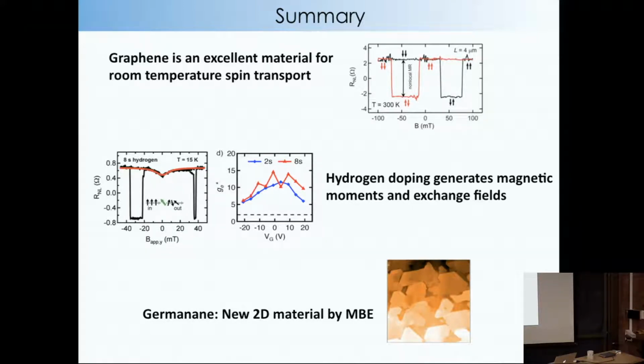It's actually a really great system because the sp3 bonding is the thermodynamically preferred state for germanium and silicon, but not for carbon. Actually, carbon wants to be more like graphite. But yes, you can do carbon; if you put enough hydrogen on it you've got a monolayer. People started by doing all this type of work with hydrogen on graphene, but the changes that you get are really drastic. It's like from conducting to insulating. You could see how it changed the resistivity by a lot, and also that system is not thermodynamically stable. You heat it to room temperature and the hydrogen shoots back off. So this, in principle, is a much, much better system to be trying to play these games, stronger with the germanium.